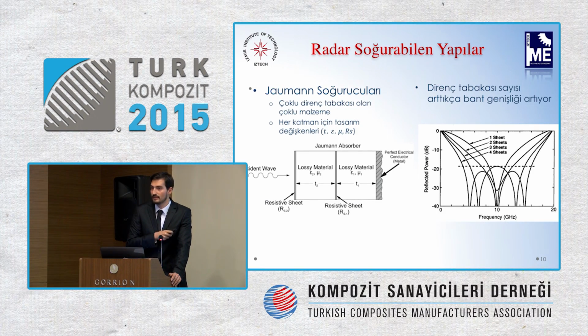developed absorber is Jaumann absorbers. They have additional resistances and the number of layers increase. What does that enable? I would like to share a graphic with you. Well, this is the frequency on the bottom line. The radar frequencies are used from 0 to 20, and this is the reflected power. It's a decibel logarithmic graphic. 10 decibel equals to 90% of loss, and 20 equals to 99% of loss.